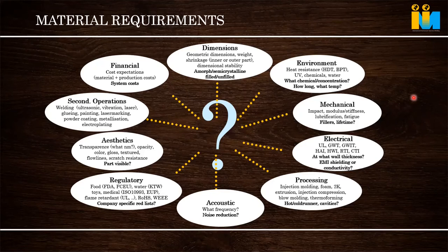And if you use PC instead of that, thinking it has higher impact, it cracks. The moment it touches, after maybe 5 to 10 minutes, the crack starts propagating. If you are using oil or grease or petrol or something in polycarbonate or most of the amorphous materials. So that selection is also very important.